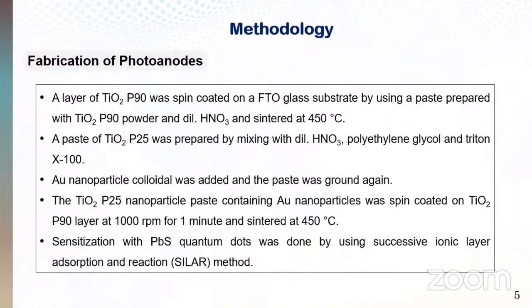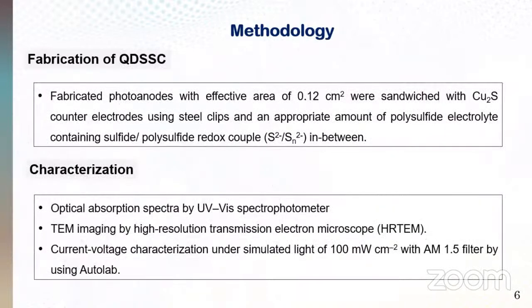Different amounts of gold nanoparticle colloidal were added and the paste was ground again. The TiO2 P25 nanoparticle paste containing gold nanoparticles was spin coated on the TiO2 P90 layer at 1000 rpm for 1 minute. Finally, the electrodes were sintered for 45 minutes at 450 degrees Celsius. In order to assemble the complete photovoltaic device, fabricated photoanodes with effective area of 0.12 square centimeters were sandwiched with copper sulfide counter electrodes using steel clips, and an appropriate amount of polysulfide electrolyte containing sulfide/polysulfide redox couple was injected in between.